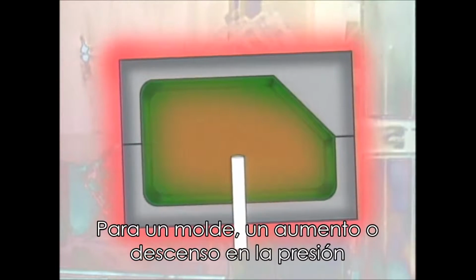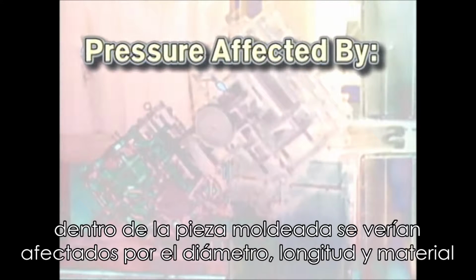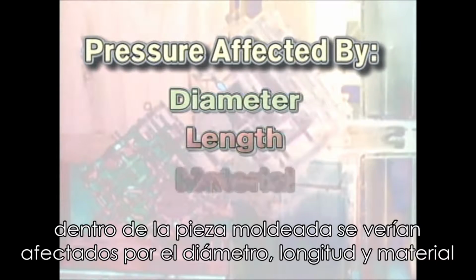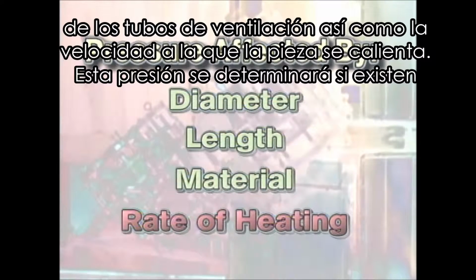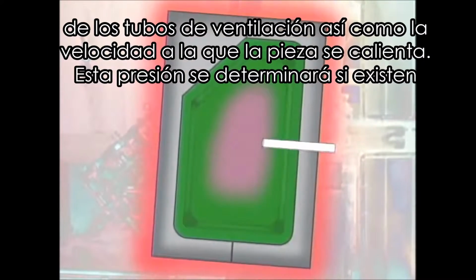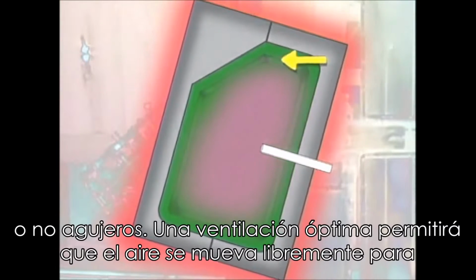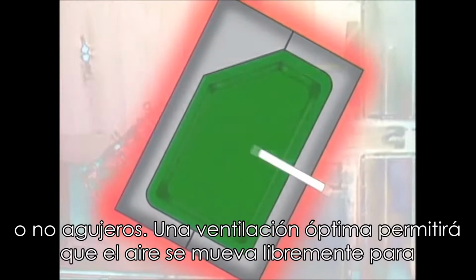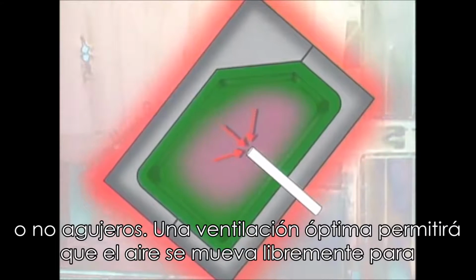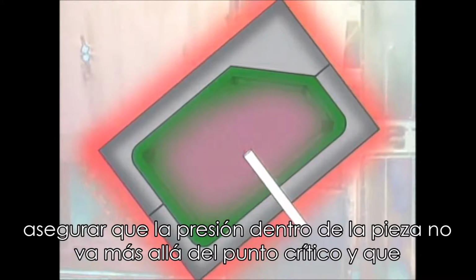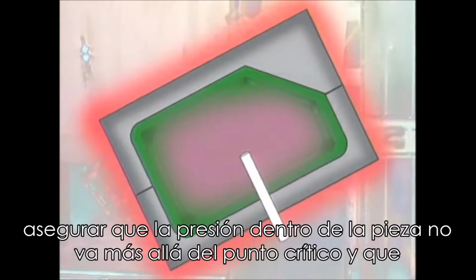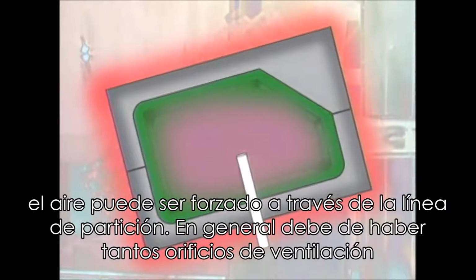For a given mold, a rise or a drop in the pressure inside the molded part will be affected by the diameter, length, and material of the vent, as well as the rate at which the part is heated. This pressure will determine whether or not blowholes occur. An optimum vent will allow air to move freely enough to ensure that the pressure inside the part does not go beyond the critical point at which air can be forced through the parting line.